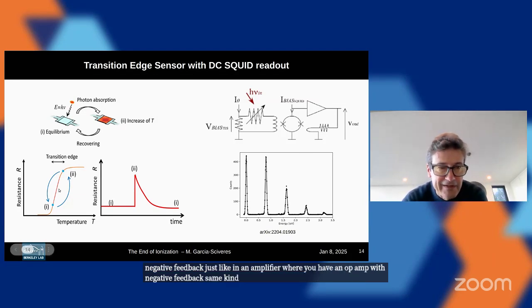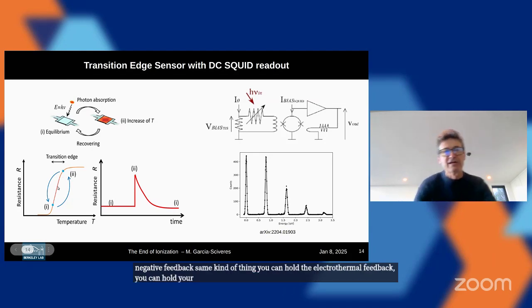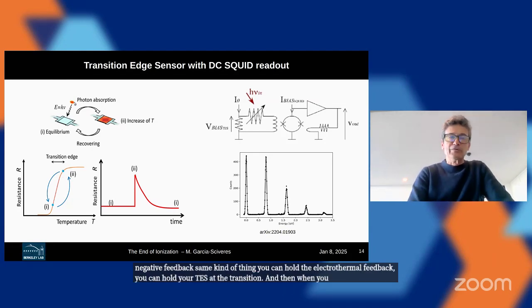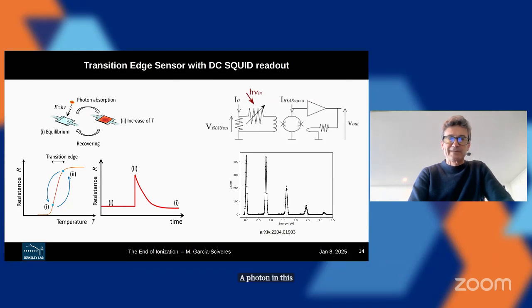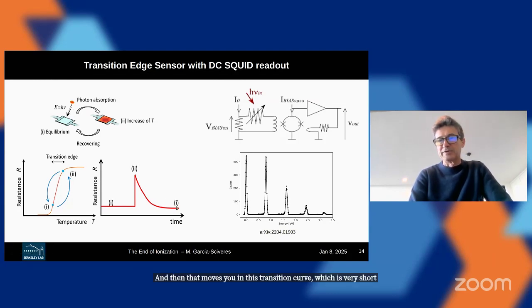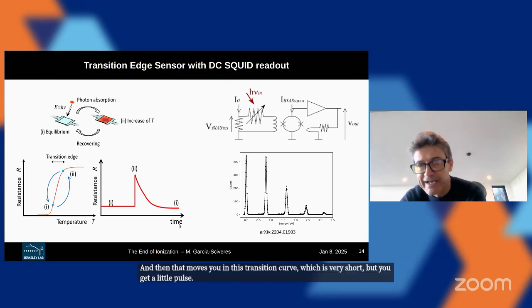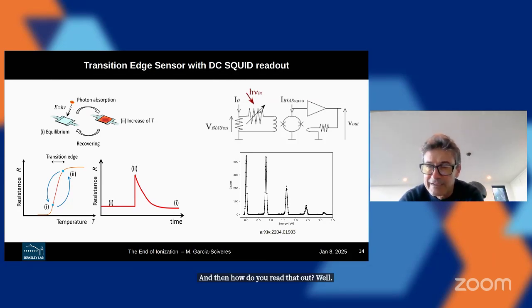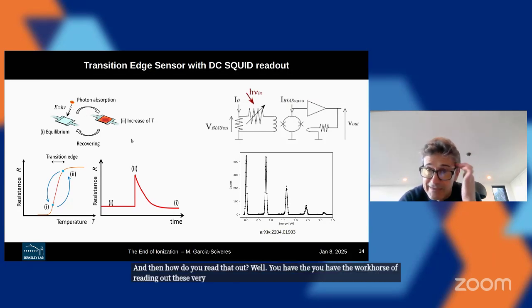You can hold, with electrothermal feedback, your TES at the transition, and then when a photon, in this case, hits the material, it gets absorbed, raises the temperature, and that moves you in this transition curve, which is very short, but you get a little pulse. And then how do you read that out? Well, the workhorse of reading out these very cold transition sensors is SQUID amplifiers.